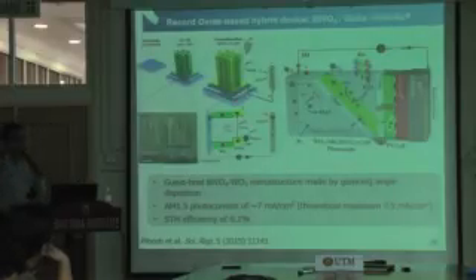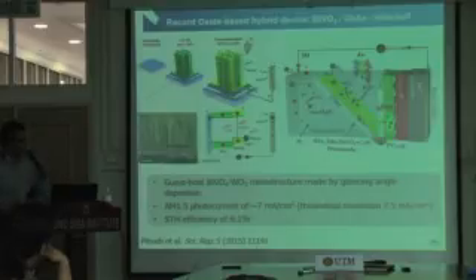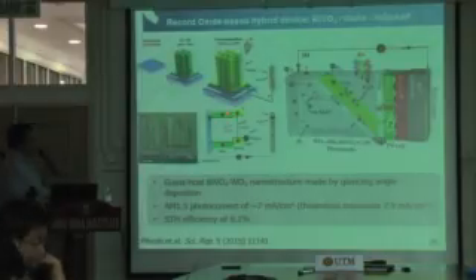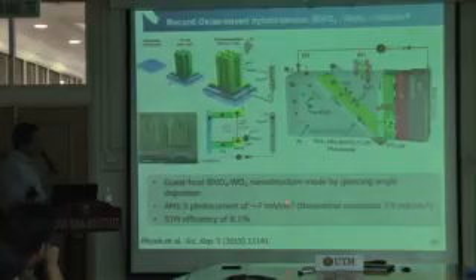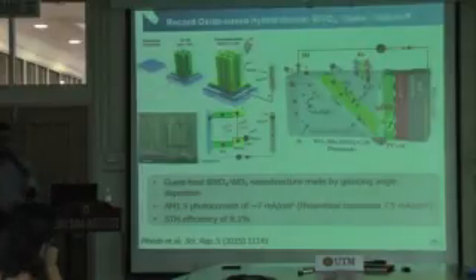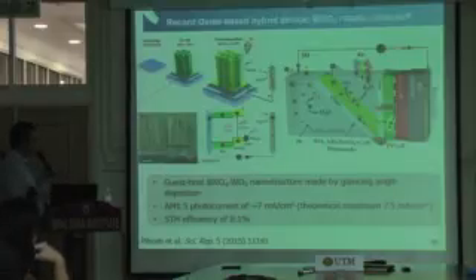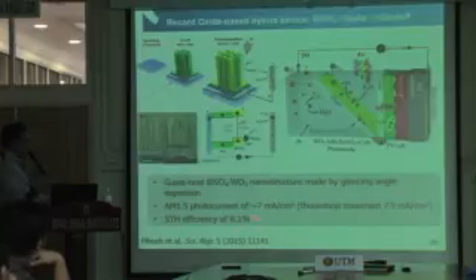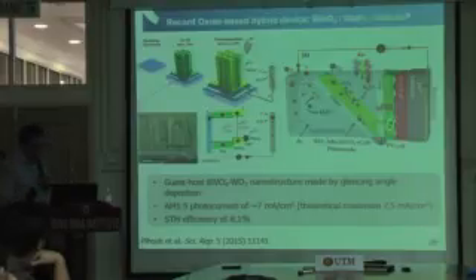It has overcome these arguments, because it is shown that with different strategies, metal oxides, which are indeed very poor semiconductors, you can manage to collect 90% of what is theoretically possible. Talk about a shocking result, that was never expected. So that gives us confidence on working on metal oxides this way. And a solar-to-hydrogen efficiency of 8.1% is achieved. Alright, so that's the first part on what has been done so far.